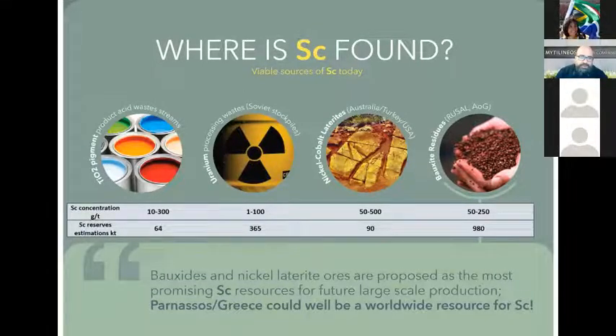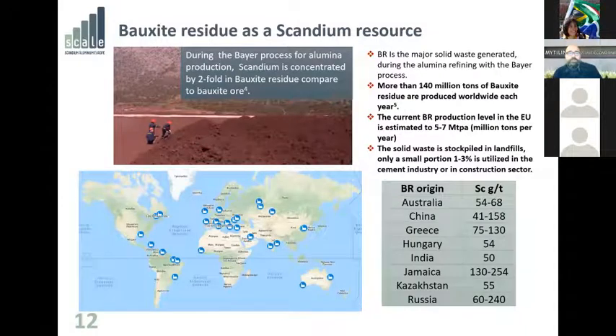You can see here an indicative estimation of the concentration of the scandium in the various sources, and also the estimation of the reserves. As you can see, while the nickel cobalt laterites could have very high concentrations, they lack in reserves. The same with the TiO2 pigment acid wastes. So, bauxite residue could be a resource for scandium and for other rare earths. As I said before, during the Bayer process for the aluminum production, scandium and all the other rare earths are basically concentrated 2 times compared to the initial bauxite ore.